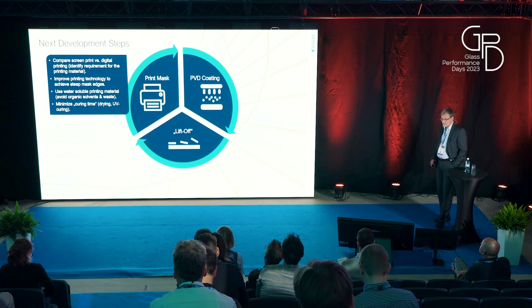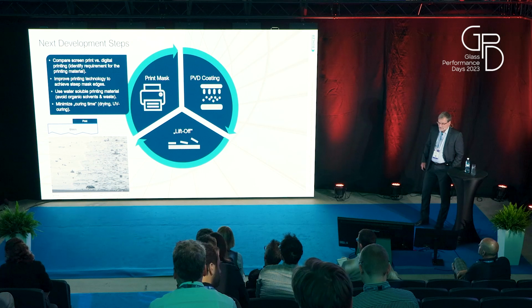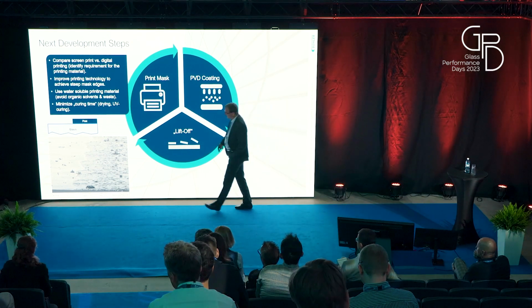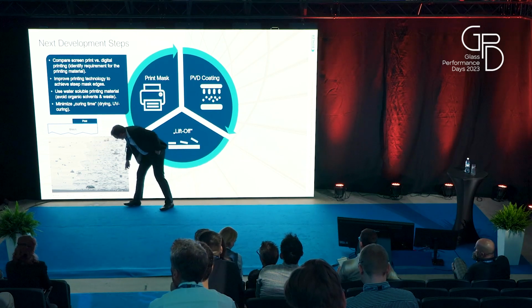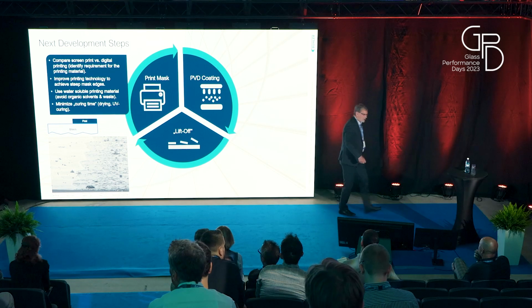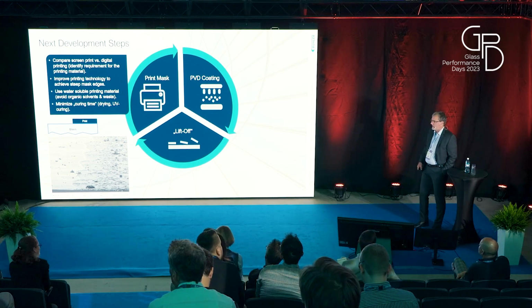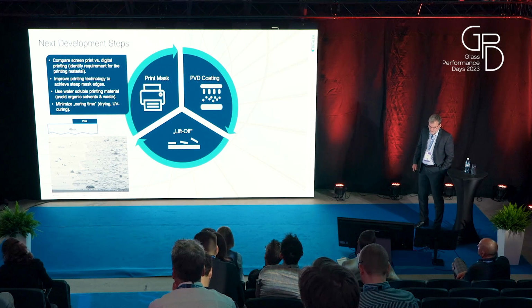And what do I mean with this? So I was always drawing the masks like this, like nice rectangles, right? But then you see actually the mask here, and it's really at the bottom. This is the glass surface, this here is the mask, and you see the thickness here. So this is a really shallow slope. And now you can imagine a thicker dielectric coating in a range of microns, maybe you cover this completely and then we have no chance anymore with lift off. So this is really a wide field we have to take care of.